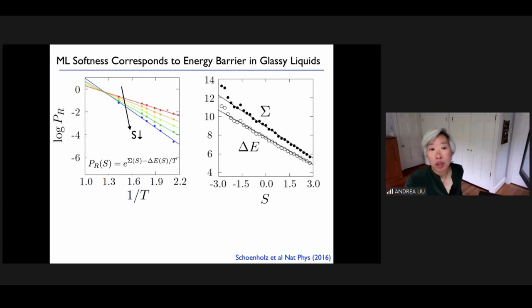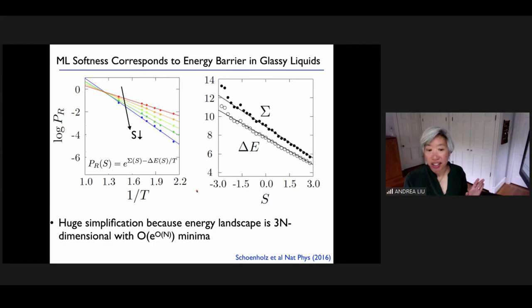Okay? So high softness particles look like this, low softness particles look like this. And if you plot the energy barrier, for example, as a function of softness, what you see is that it is lower for particles of high softness than for particles of low softness. Okay? What is the advantage of this? Well, the energy landscape is a 3N-dimensional landscape. It has of order e to the order N minima, a huge number of minima, and trying to calculate the energy barriers is a very laborious task, right? And so the idea of this is that simply by looking at the structure, very simply calculating this local pair correlation function, you can get an idea of the energy barrier that the particle needs to overcome in order to rearrange.